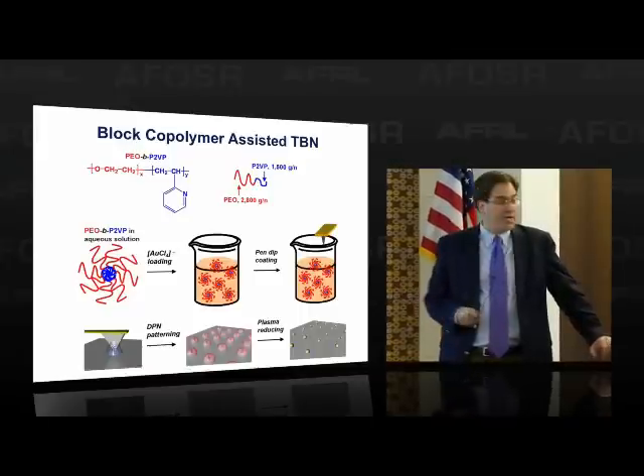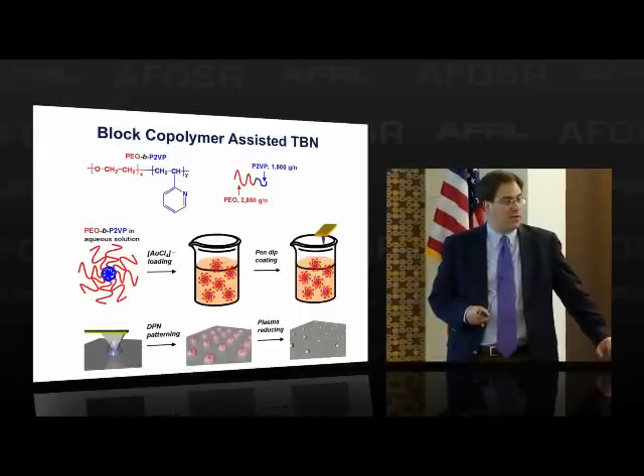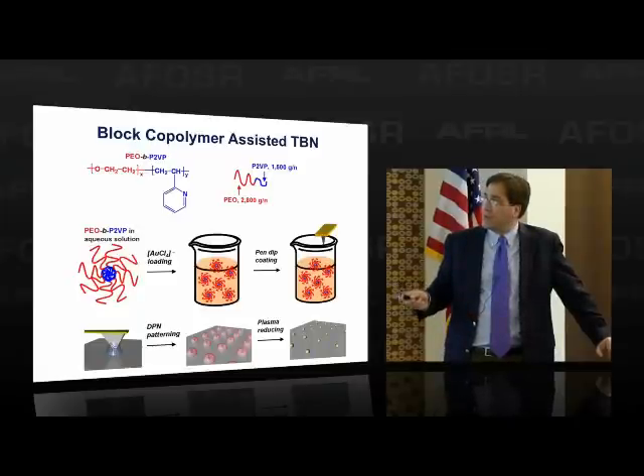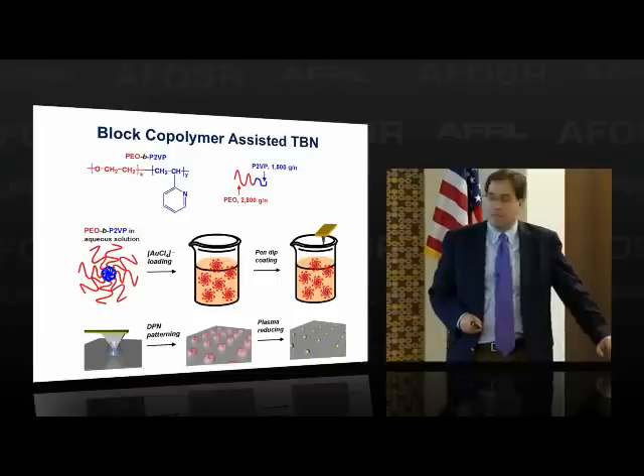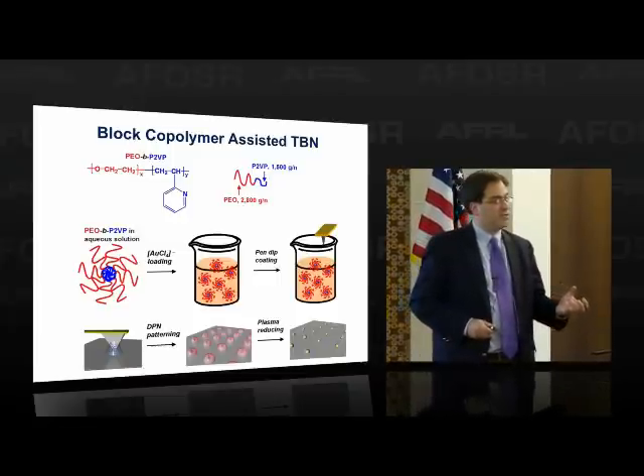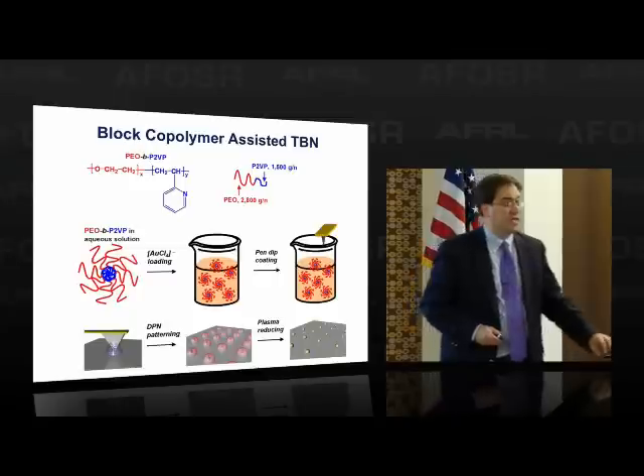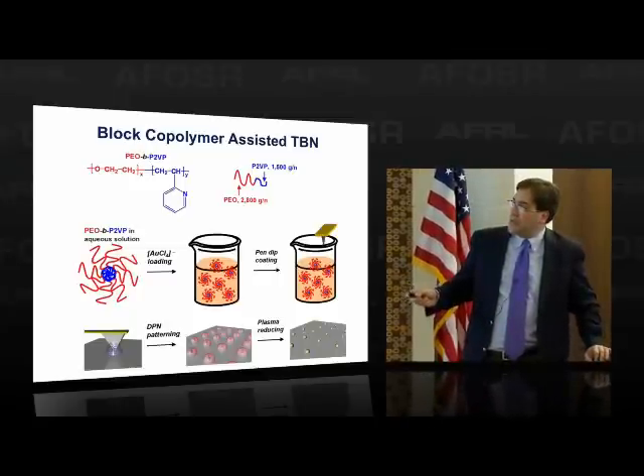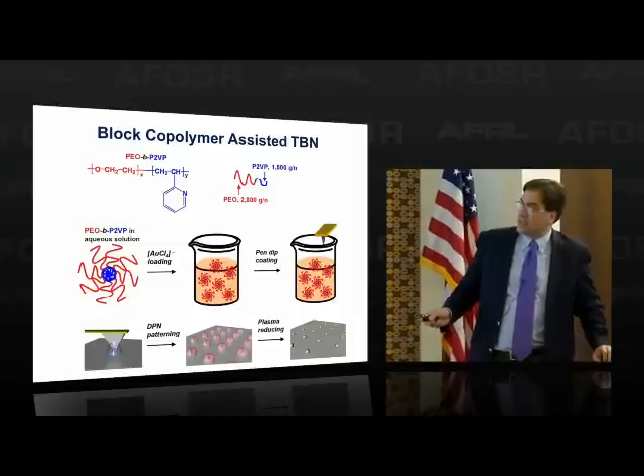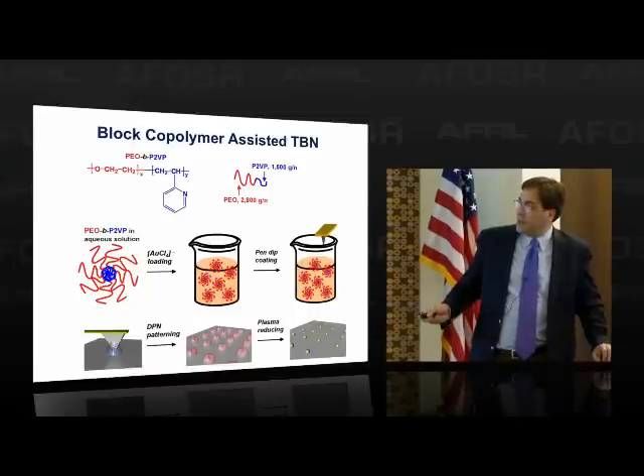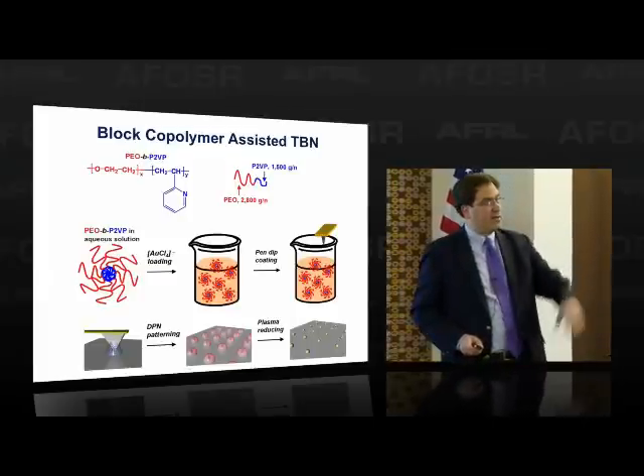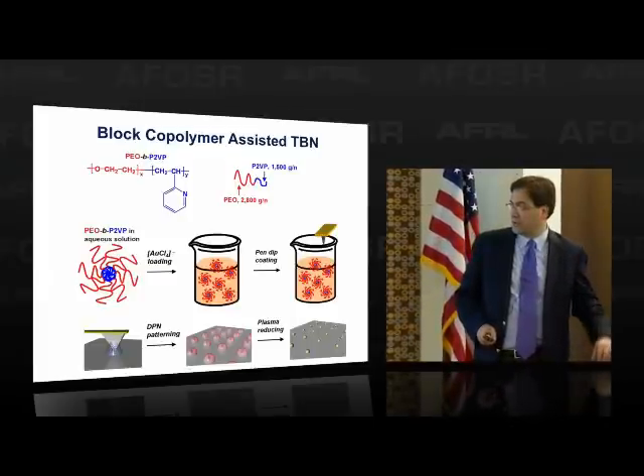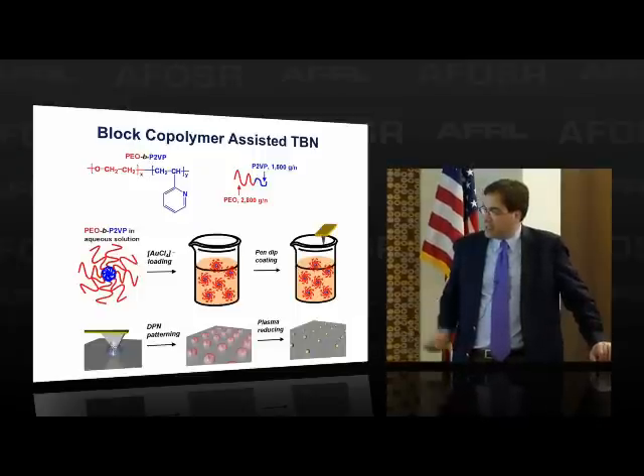But here we took a page out of what's called the block copolymer lithography area, where we said maybe what we could do is create a polymer that was designed to flow. So we have a polyethylene oxide over here, and poly-2-vinyl pyridine as a block that was designed to pick up something that was going to be used as a synthon to make a resulting structure, let's say a metal ion. And so if we take this and put this, for example, in water, these will form micelles. We can load them up with metal ions because the metal will bind to the pyridine in this case. And now we can put these on tips, either a cantilever or the polymer pen arrays that I showed you, or the hard tip on soft backing arrays, pattern on a substrate,